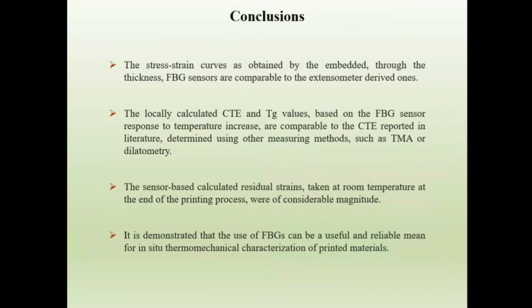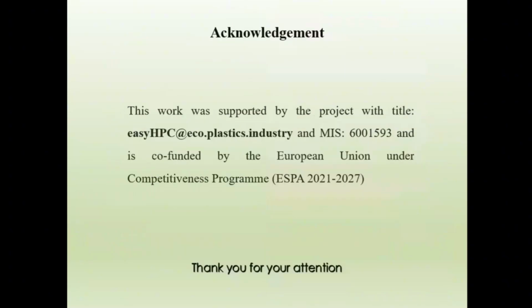So these are the general conclusions. Personally, I was expecting to see some significant differences between the first layer and the one close to the top. And it was really interesting to get the outcome that by doing classical testing using an extensometer, we can get the mechanical response that seems to be that of the material in different layers. Of course, this was placed in the framework of an industrial work.